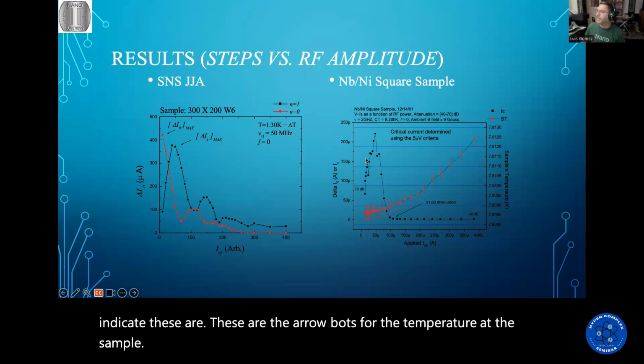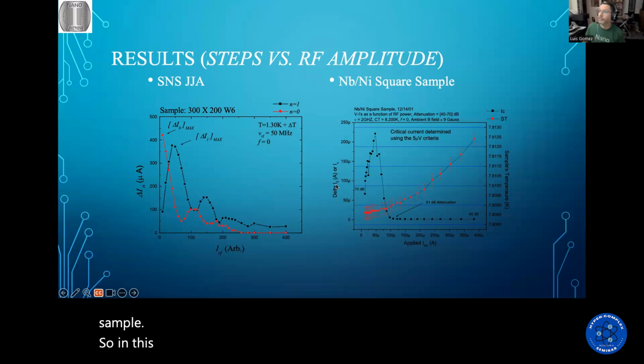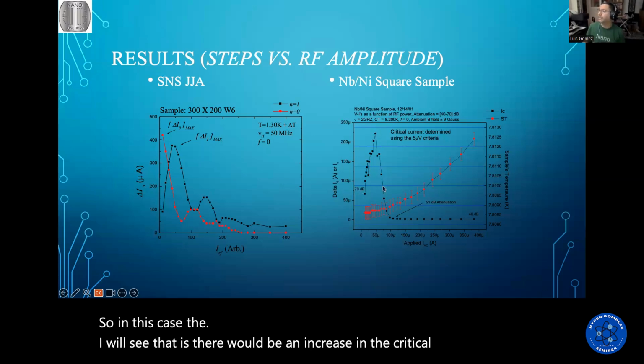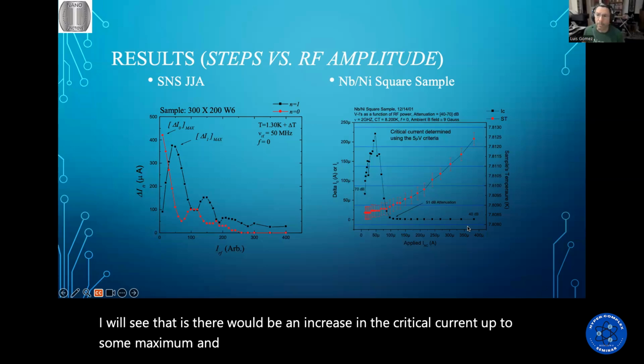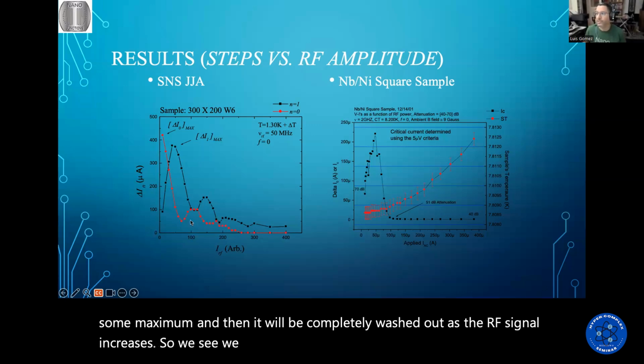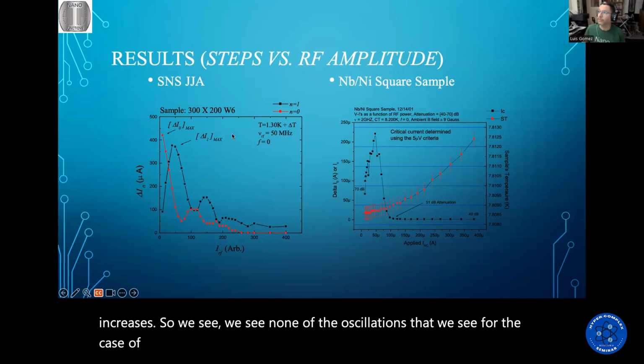In this case, I will see that there will be an increase in the critical current up to some maximum, and then it will be completely washed out as the RF signal increases. So we'll see none of the oscillations that we see for the case of the steps. Let me see what time I have.